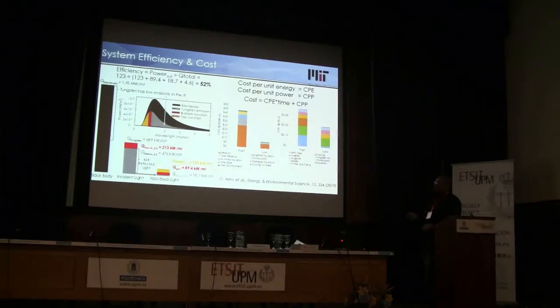One of the things that we can do to affect this is the point I made about the fins on the tungsten. So if we can increase the area ratio between the PV and the emitter, we can increase the overall heat flow above the band gap, or it's the total heat flow, it's not just above the band gap. Then the below band gap is almost 500 kilowatts per square meter.